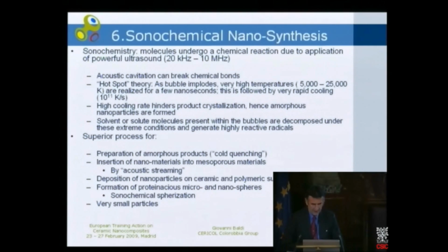Finally, let me introduce an interesting synthetic route named sonochemical nanosynthesis. In sonochemistry, molecules undergo a chemical reaction due to the application of powerful ultrasound, normally in the range of 20 kilohertz to 10 megahertz. In this case, acoustic cavitation can break chemical bonds.